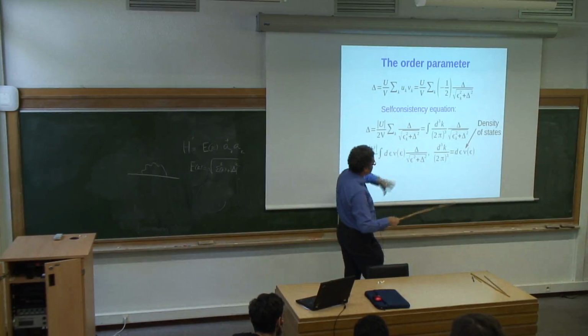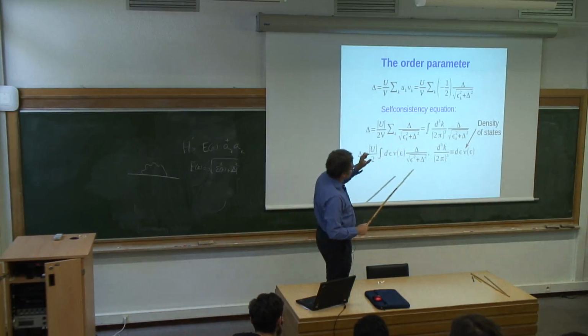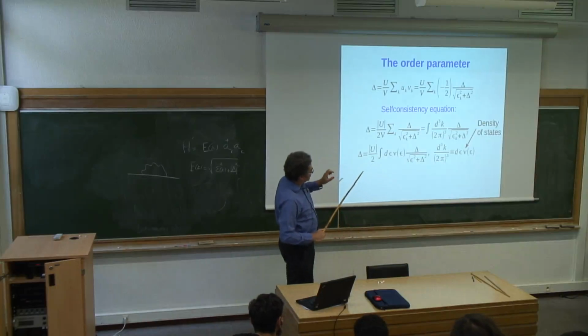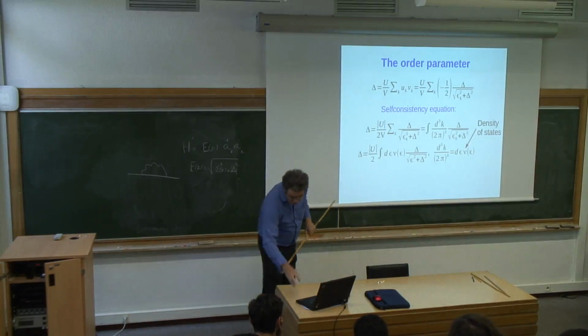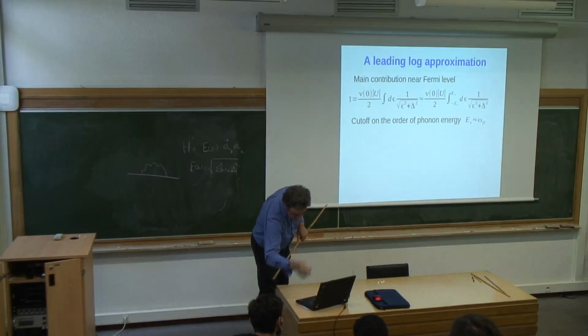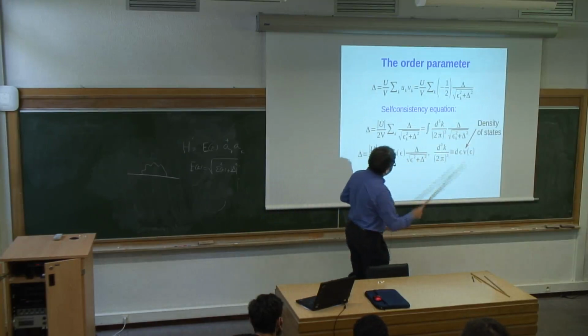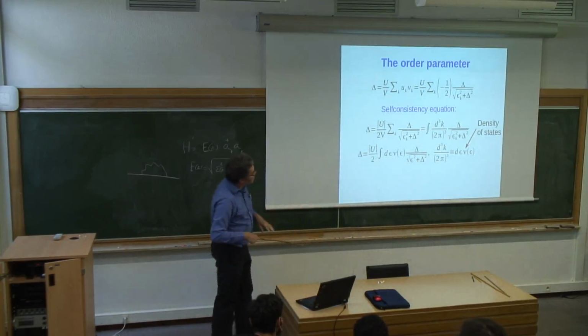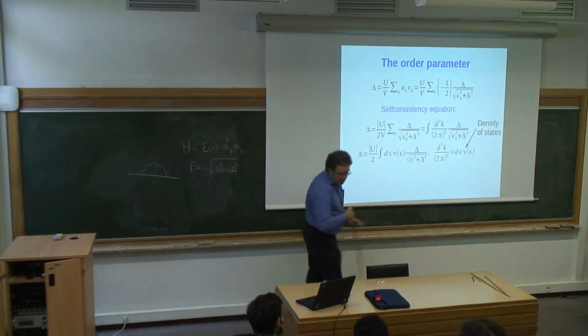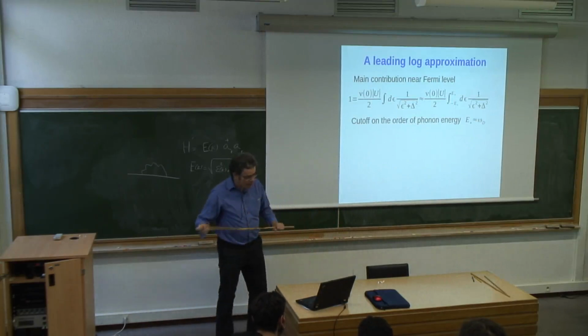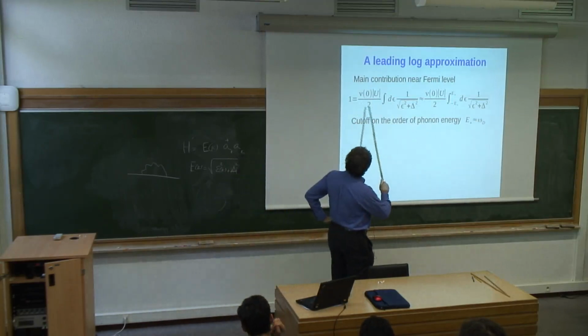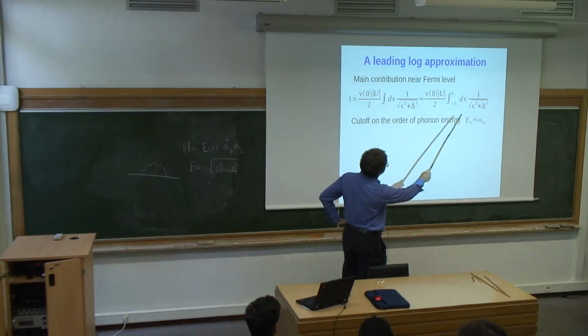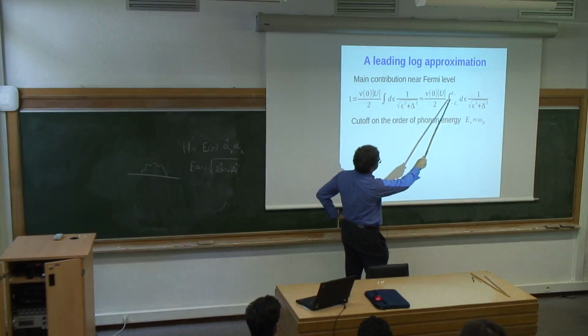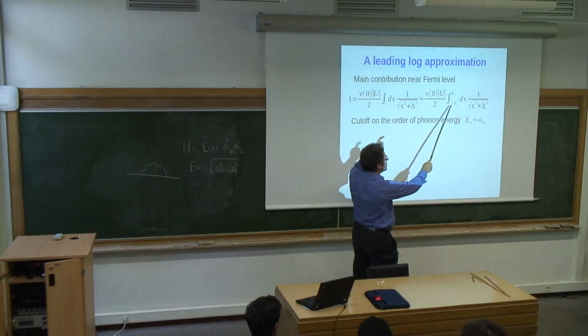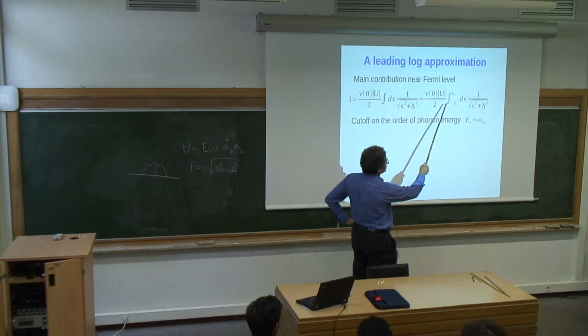So even though there is an integral over all states, one can show that only the vicinity of the Fermi surface matters, and because of that, it's convenient to simplify the integration and go to the vicinity of the Fermi level by replacing the integral over three-dimensional k-space by an integral over one-dimensional energy multiplied by the density of states. And if you do that, you get a contribution of states near the Fermi level in this form.